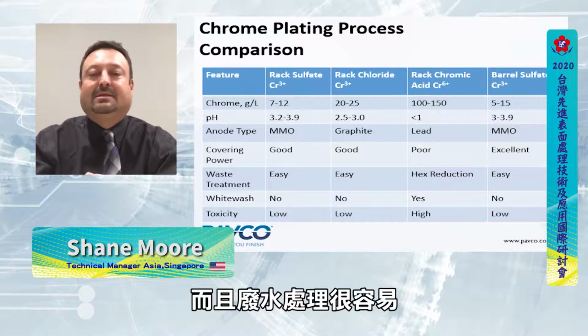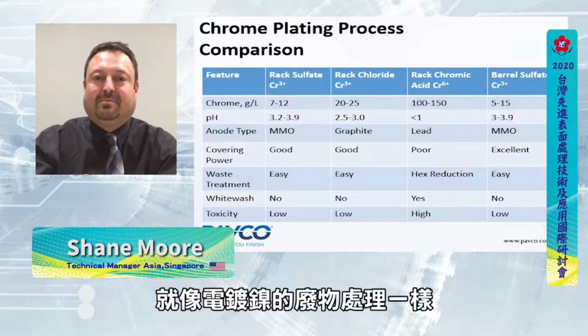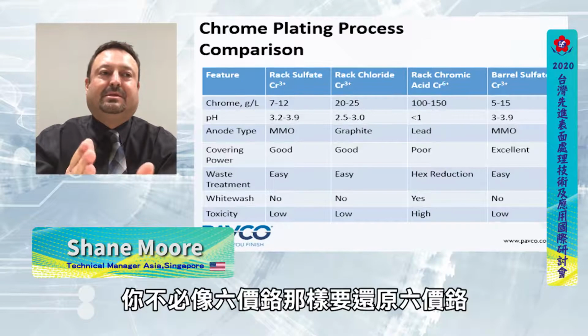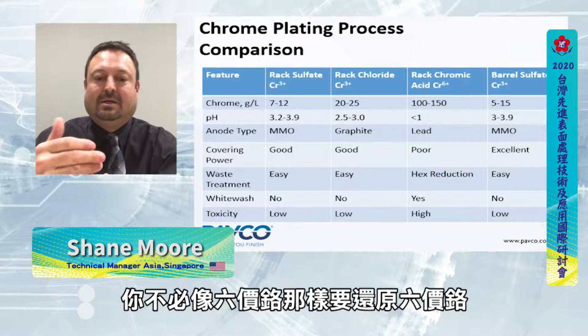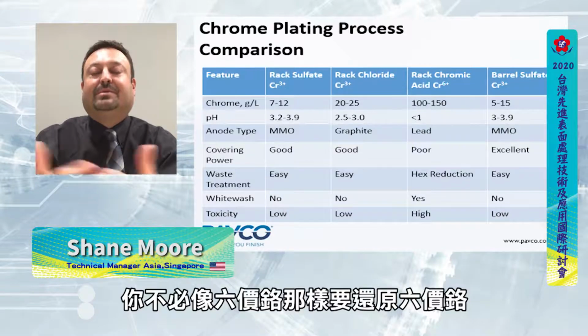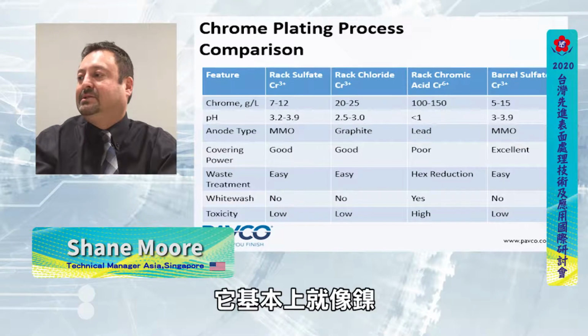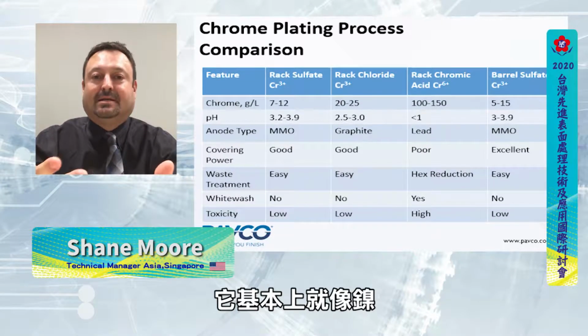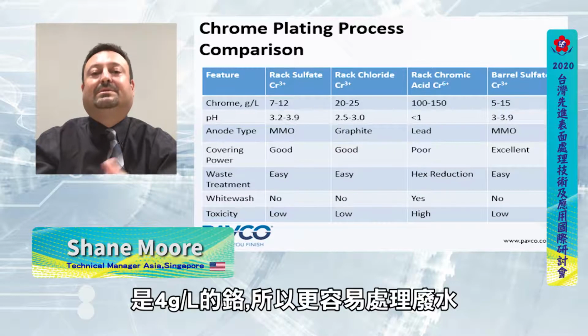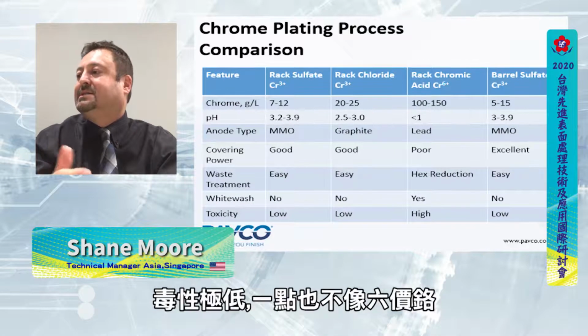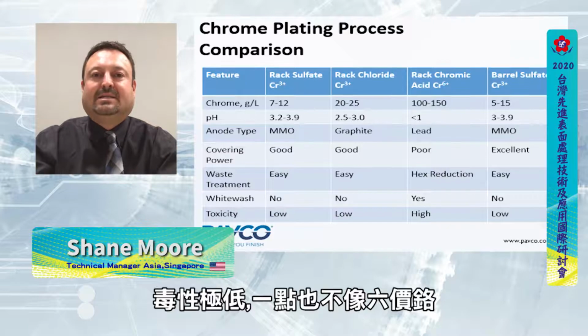Waste treatment is pretty easy. It's like waste treating a nickel bath. You don't have to do the hexavalent chromium reduction like you do with hexavalent chromium. It's basically like nickel, and like I said, it's only 4 grams per liter of chrome, so it's much easier to waste treat. The toxicity is extremely low. It's nothing like hexavalent chromium.